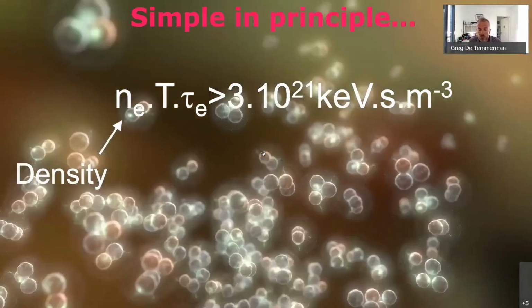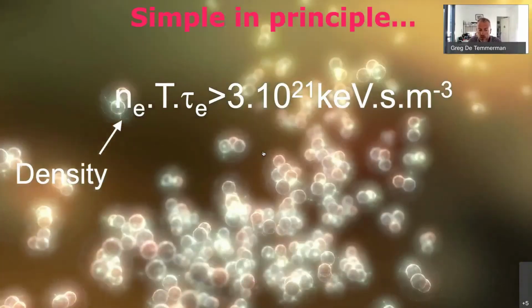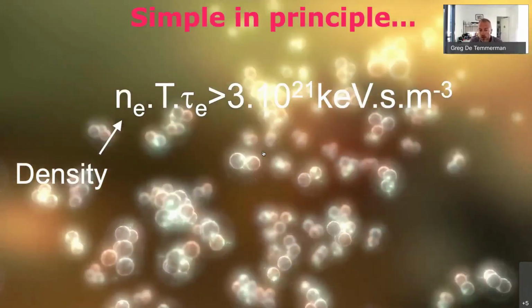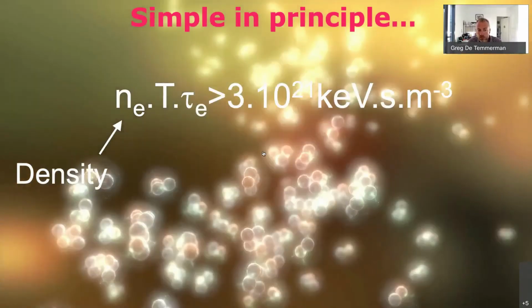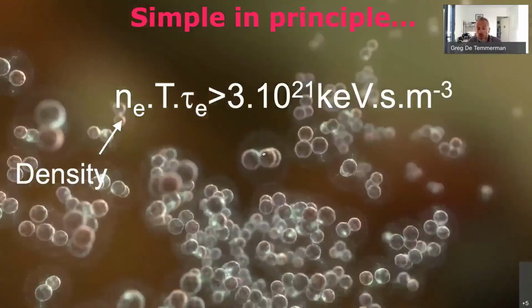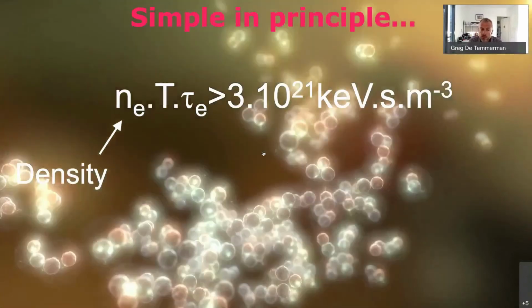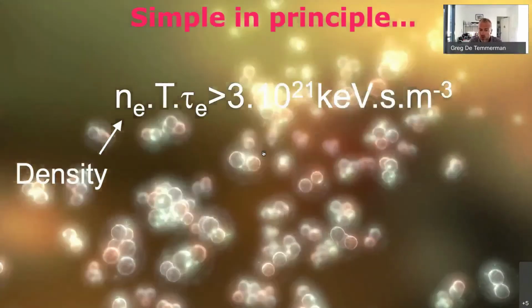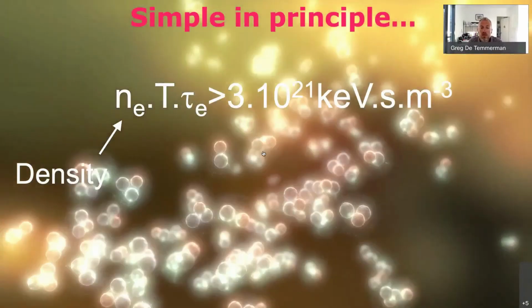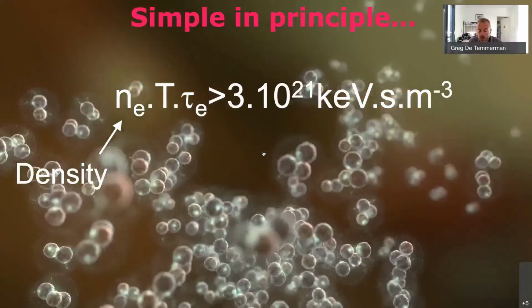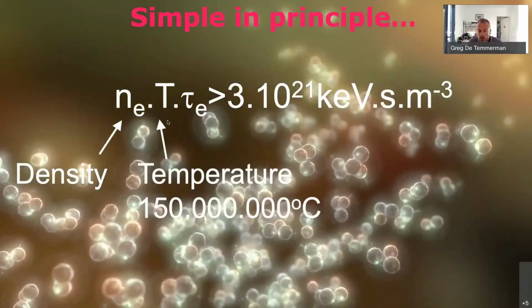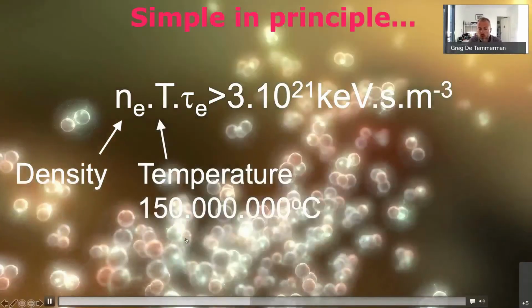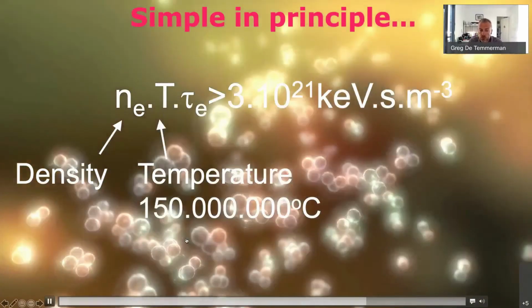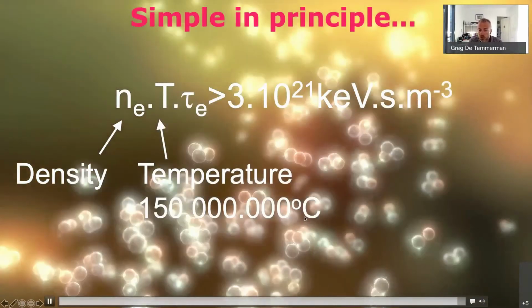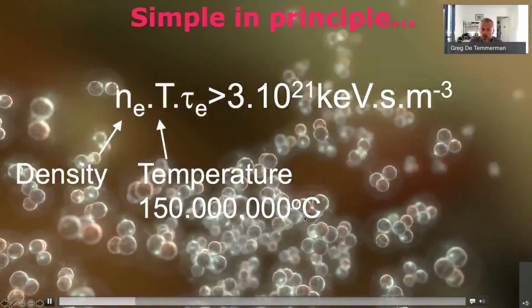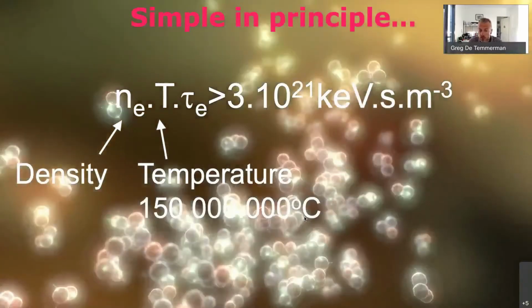So you have to have a certain number of particles in a certain volume. In what I will be talking about, we have actually very low densities. So we have densities which are typically 1,000,000 times or even more lower than the density of the air in the room where you are. So we work at very low density, but we work at very high temperature. The temperatures we have to reach on Earth for deuterium and tritium to fuse is typically in the order of 150 million degrees, which is 10 times higher than the temperature inside the core of the sun.